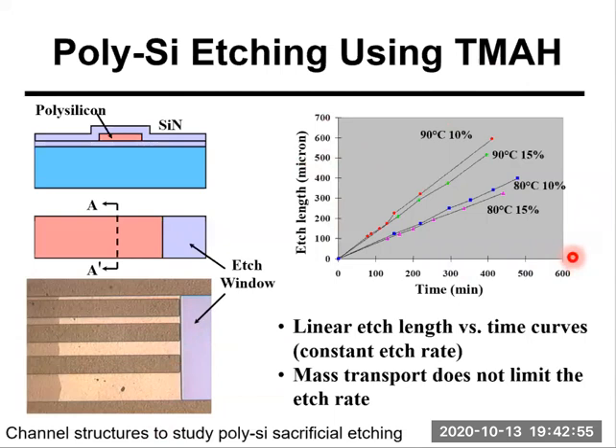This figure plots the etching length, this distance, as a function of time. And it's very interesting that now we observe linear etching length versus time curves, which means the etching rate is constant. The etching rate remains constant over time or over the etching length. Then we can conclude that for polysilicon TMAH etching inside a microchannel, mass transport does not limit the etching rate.